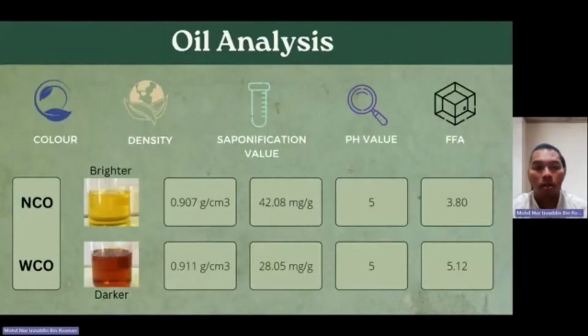Okay, for the oil analysis, as you can see, for the color, new cooking oil has a brighter color compared to the used cooking oil, which has a darker color. It's because the used cooking oil has been used many times, which changes the color to darker. But for density, both oils have a similar density of 0.9, and the same pH value of 5.